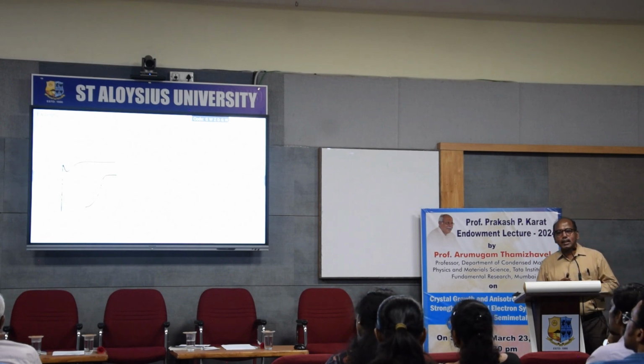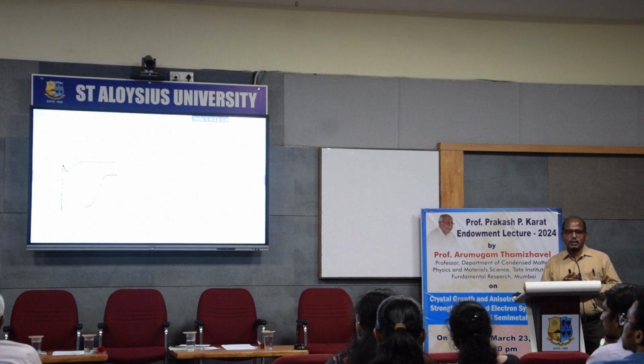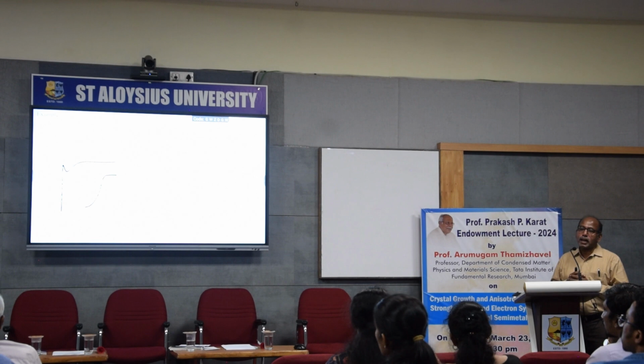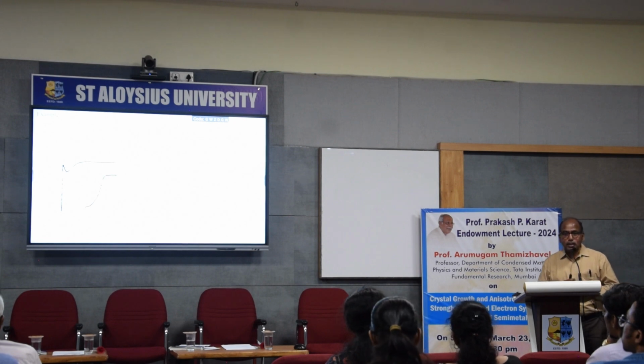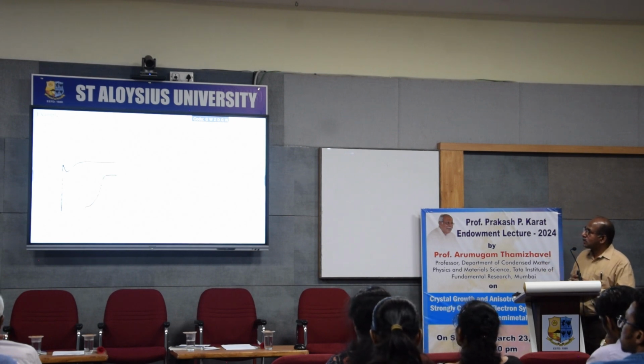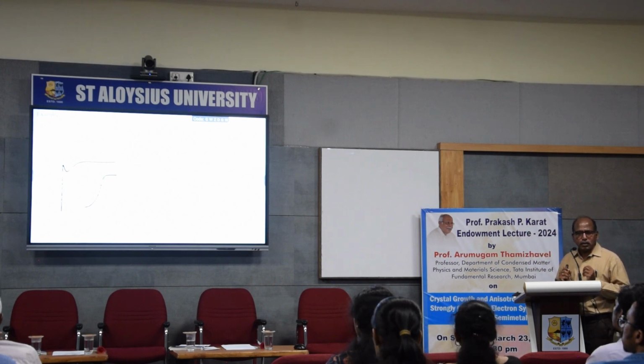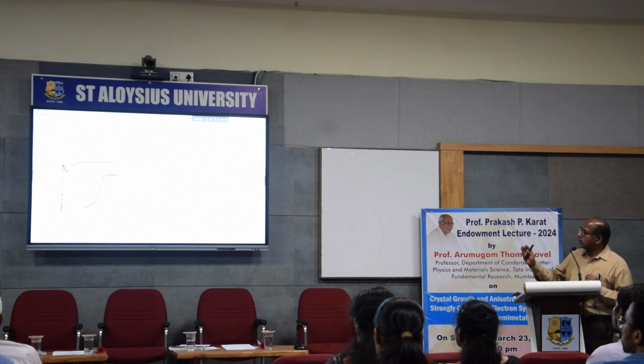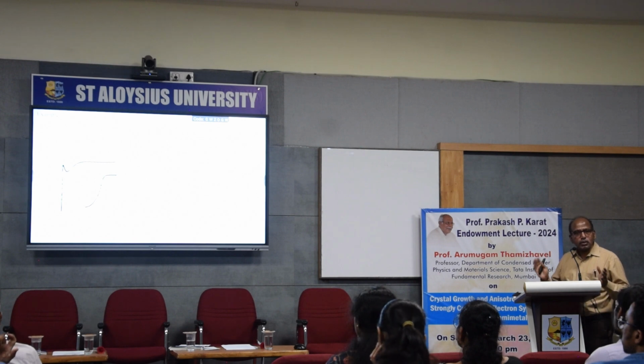Having said this about the single crystal, what is so important with a single crystal? Why do I bother about a single crystal? Why is there so much hype about a single crystal? This example will tell you why we need to have a single crystal. This is an electrical resistivity diagram of a sample named cerium-2 nickel-3 germanium-5. This is an intermetallic compound. I measure the electrical resistivity from 300 Kelvin to 2 Kelvin. I have made a polycrystalline sample. I know that it is not a single crystal, it is a polycrystalline sample.